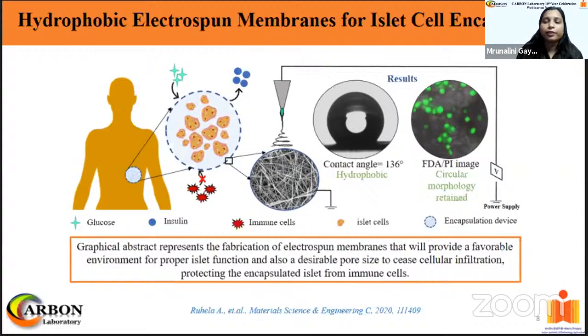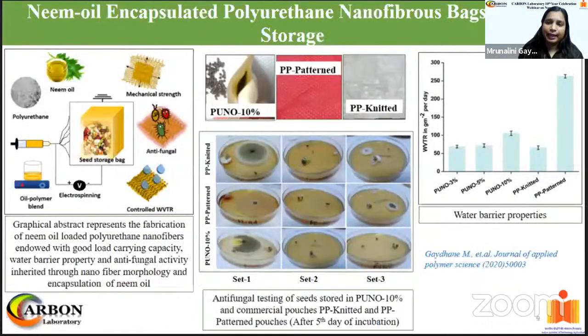Also, we introduced hydrophobicity to inherently hydrophilic polymers, which aided in maintaining circular morphology of islet cells to maintain a 3D architecture. Next, in agriculture, we fabricated neem oil encapsulated polyurethane nanofibrous bags for seed storage application. The blend of neem oil and polyurethane in dimethyl formamide solution was prepared and electrospun to obtain the nanofibers. Due to structural integration of neem oil into the soft segments of polyurethane, the load carrying capacity and elasticity of nanofibers was enhanced, which was in comparable range with commercial seed storage bags of polypropylene.